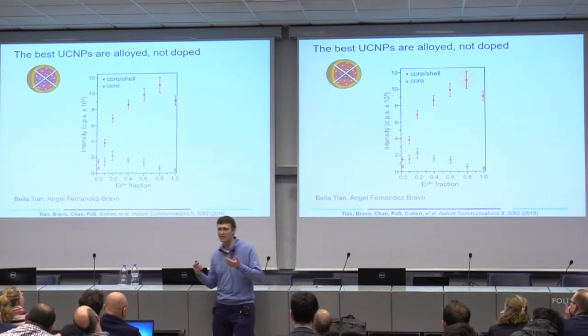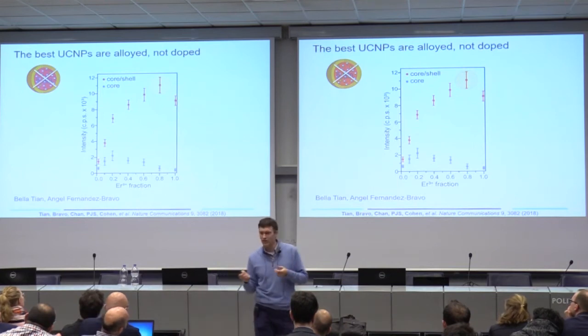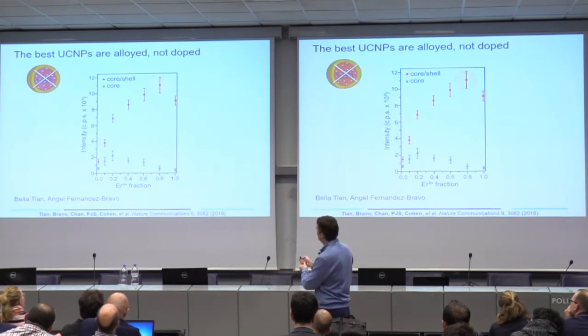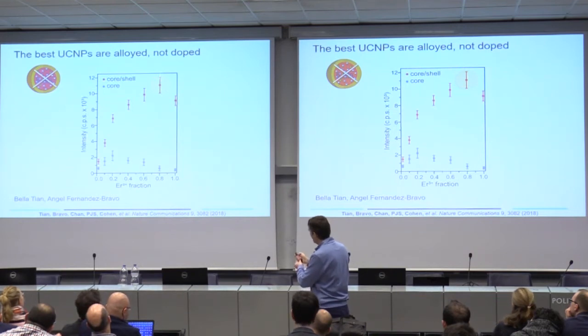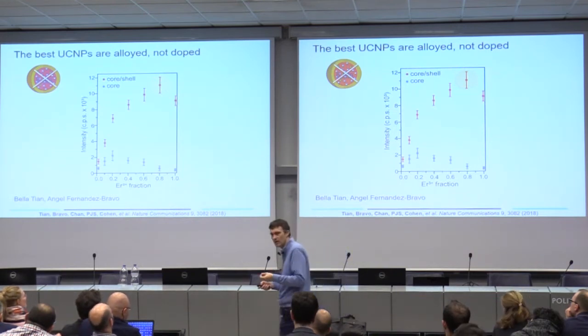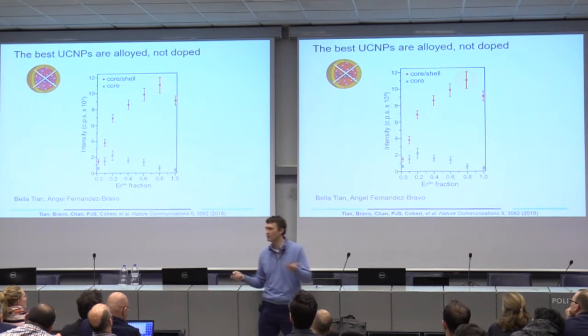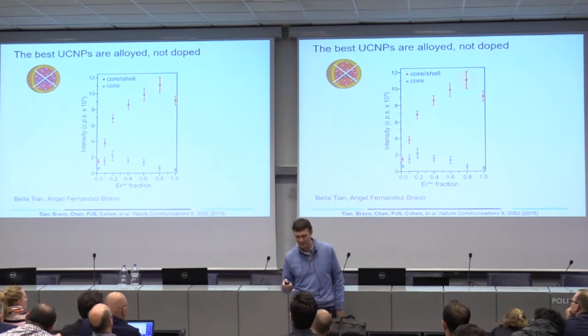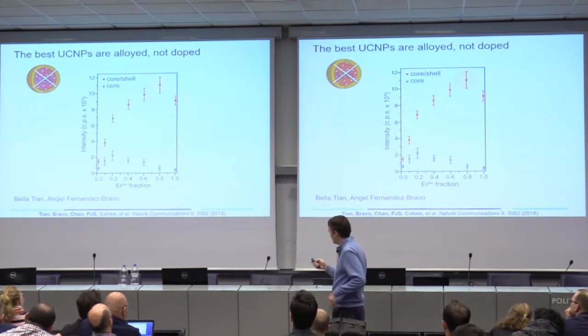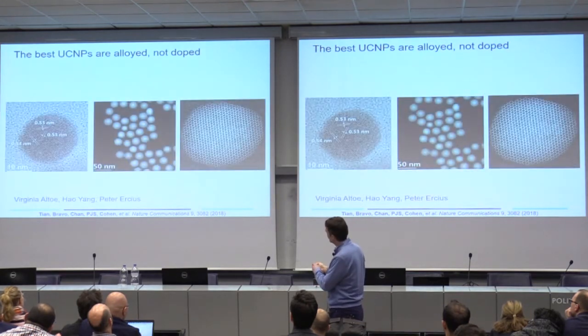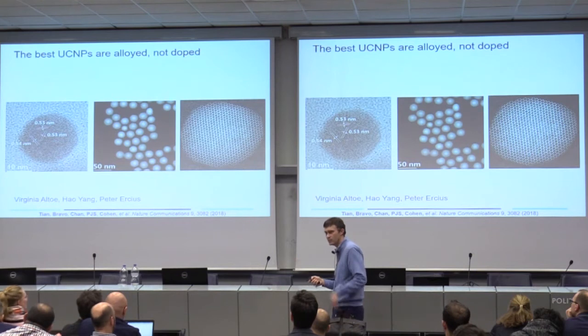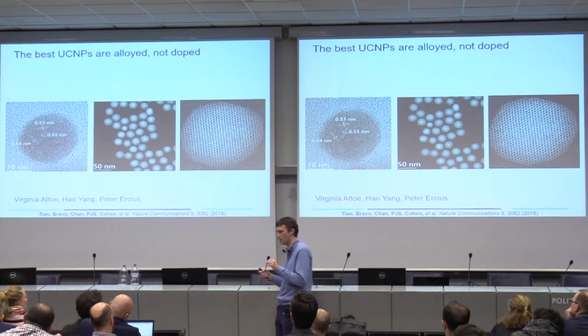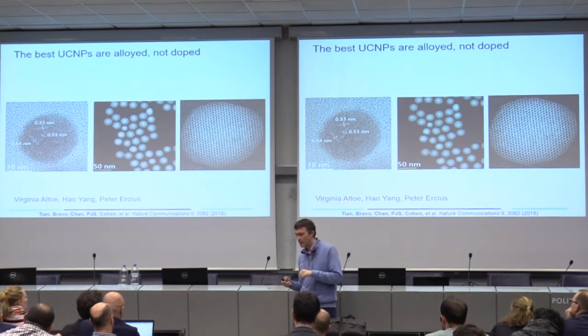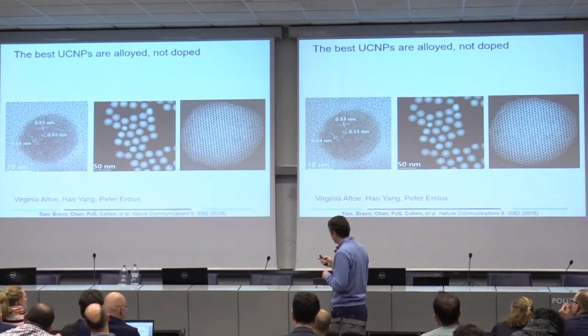So they go from being doped to alloyed materials, right? So in this particular graph from one of our papers, what you see is that the best particles were 20% ytterbium and 80% erbium. So there's no more yttrium involved anymore in these structures. And so here's what they look like. You can see there's the core. You do have to put relatively thick shells on them to really prevent the surface losses, usually about 6 nanometers or so. But by doing that, they get very bright.